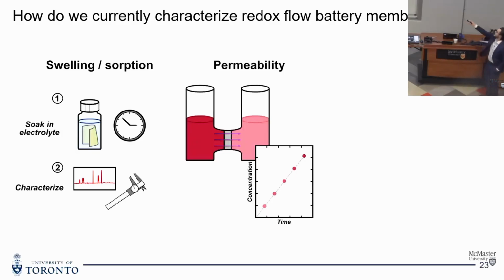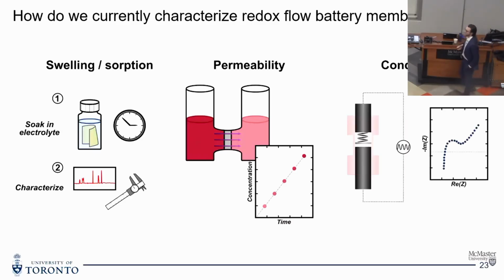You would put it in something like an H cell where you have a higher concentration on one side, a lower concentration on the other. And you just watch things diffuse across that membrane and measure the concentration versus time. The slope is proportional to the permeability. So we know diffusivity, and then we want to know conductivity. You might sandwich the membrane between two electrodes and measure something like the resistance or the impedance. And there are a dozen ways to do this. This type of sandwich cell is just one example. There are a lot of forms of conductivity measurements that all measure slightly different things.